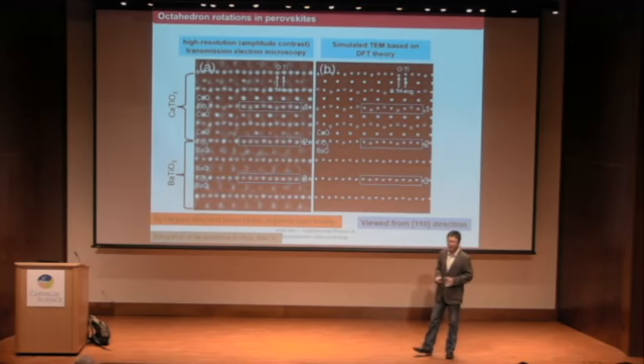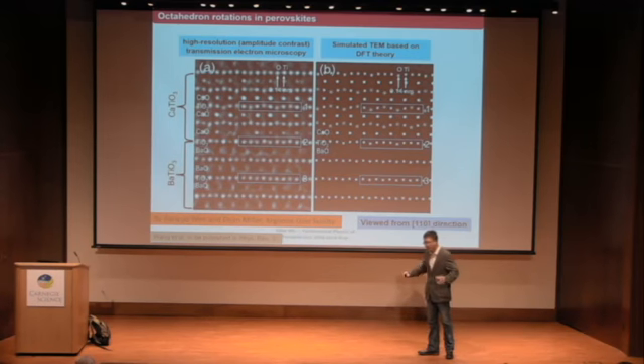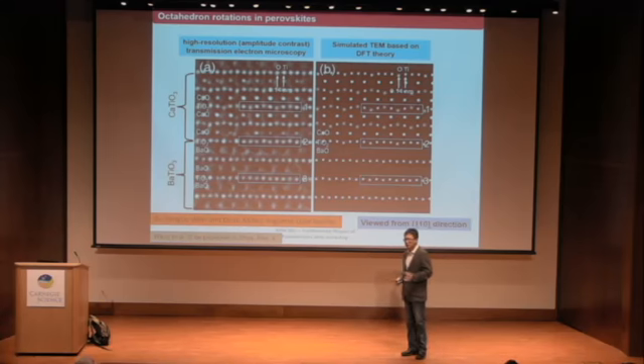Then what is the qualitative information in this image? Actually, it tells you that the TiO2 sandwiched between two BaO planes is flat, meaning there's no tilting, no antiferrodistortive rotation, etc. This is kind of expected because BTO has a kind of large tolerance factor.